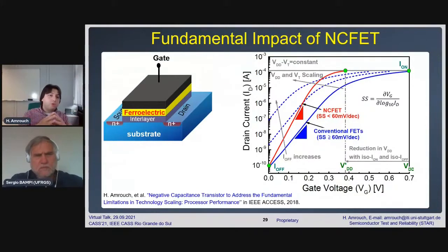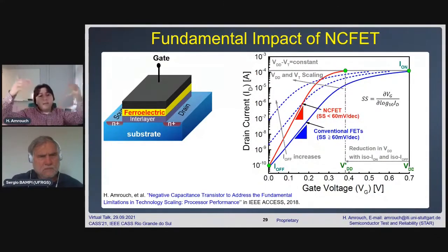Another challenge is if you really want to adopt those emerging technologies, you really need to ensure their scalability. And having an ultra-thin ferroelectric layer to allow the scaling, there is a debate about whether the negative capacitance effect could really still exist at 1 nanometer or 2 nanometer. There is an amazing work that came from Salahuddin from University of California, Berkeley, 2 years ago, or 1 year ago. He also showed that what has been believed for a long time, that ferroelectricity does not hold or will be lost at a very thin layer, could still work with lots of material engineering. So this is the biggest challenge.